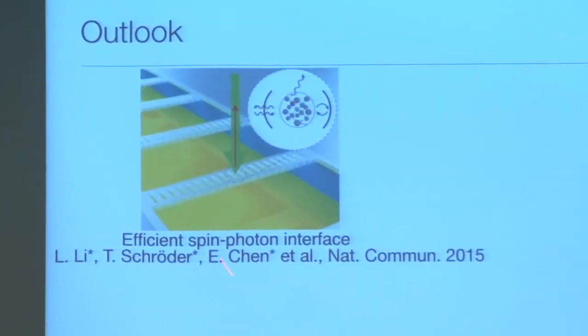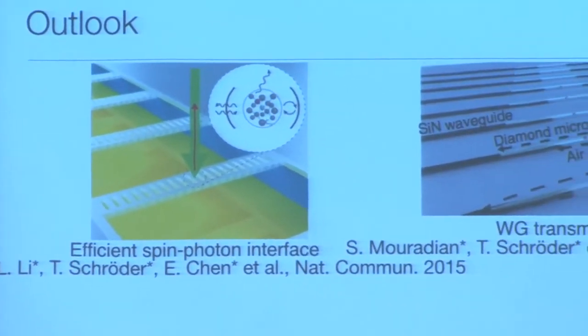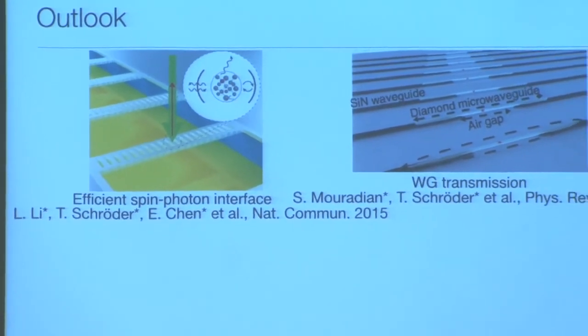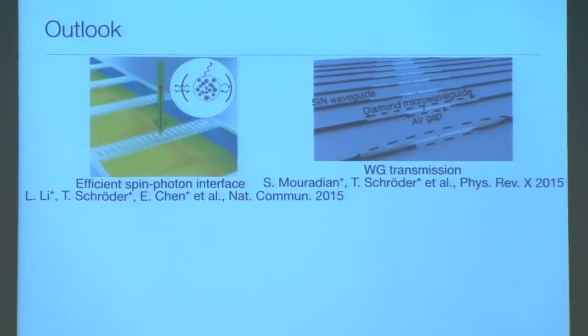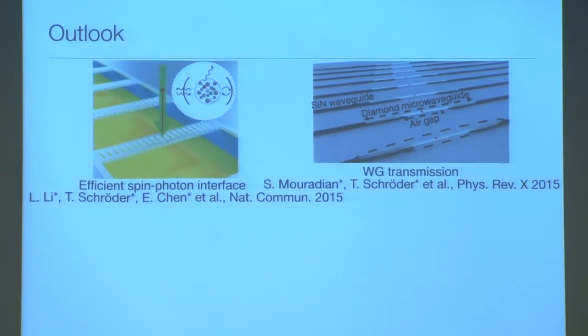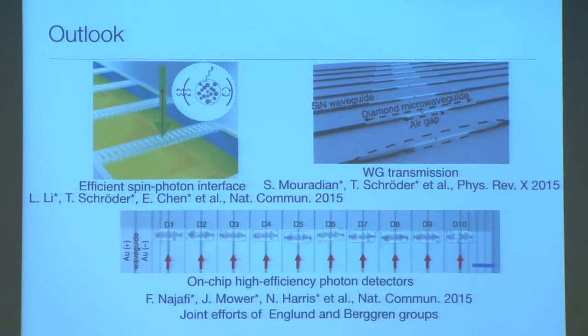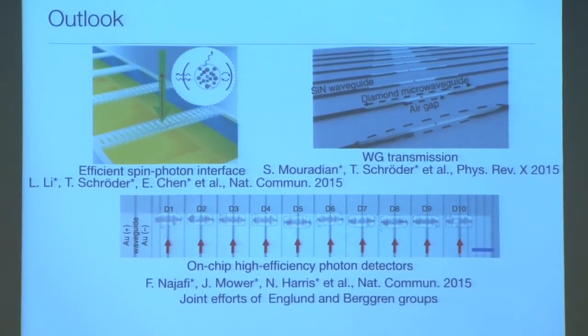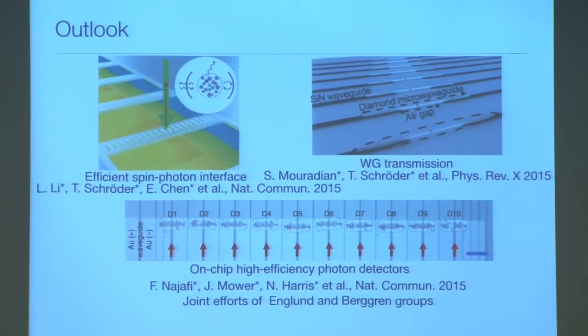At the same time, while I was working on the efficient spin-photon interface, my colleagues, Sarah and team, have successfully coupled NV centers into a silicon nitride waveguide and achieved photon transmission. And also, our joint effort between the Englund and Berggren groups has proven that we are able to fabricate on-chip, highly efficient superconducting nanowire detectors.